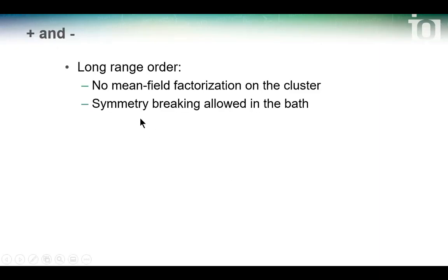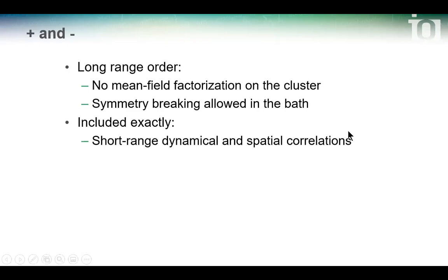Now you need to critique this method. What is the problem with these methods, or what are the advantages and the disadvantages? Advantages, what about long-range order? Well, usually to do long-range order, you do some mean field somewhere. But here we never do mean field on the cluster. The mean field is done in the bath that's supposed to represent the infinite system. So it's determined self-consistently. So symmetry breaking is allowed only on the bath. There's no mean field factorization on the cluster.